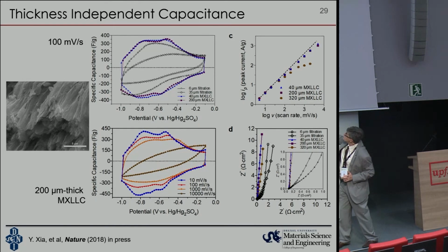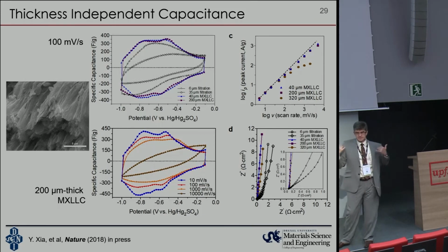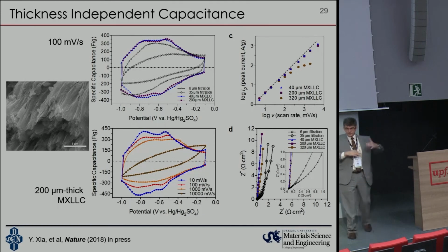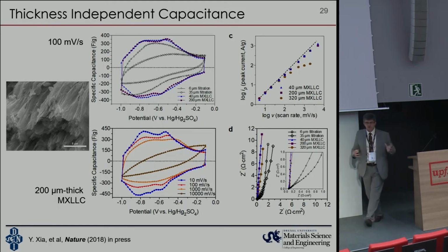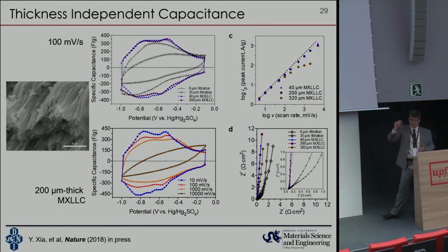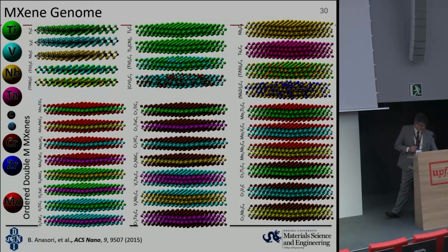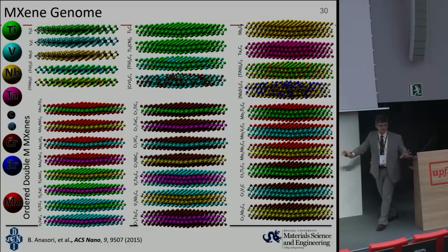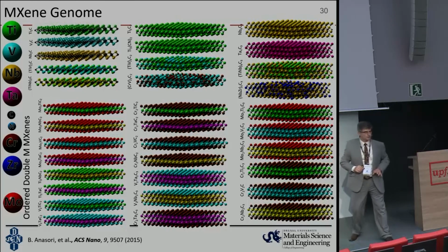There's almost no change in gravimetric capacitance when we go to much thicker film. And actually, this film shows capacitance, as Patrice mentioned before, if you densely align it, in excess of 1,000 farad per cubic centimeter here. So an order of magnitude more than we can get in the same volume for a double layer capacitor. I know it was a very, very short presentation, and I probably was too superficial to cover things in detail.